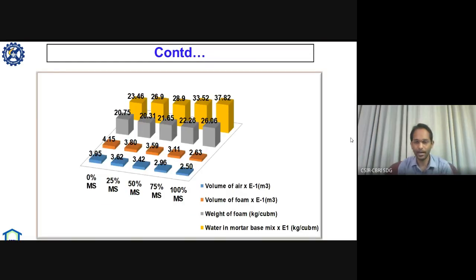So here you can see how the stone slurry affects the weight of foam. You just see the column, that blue one. As we increase the stone slurry, the amount of foam, that is the weight of foam, increases. Why was it so? Because the incorporation of slurry collapses the formed bubbles, because the particles are angular and so fine that they can penetrate and destabilize the foam generated. That's why we have added extra foam, to achieve our target density ratio and consistency of the green mix. So you can see here, as the amount of modified slurry increases, the weight of foam and the volume of foam also increase.